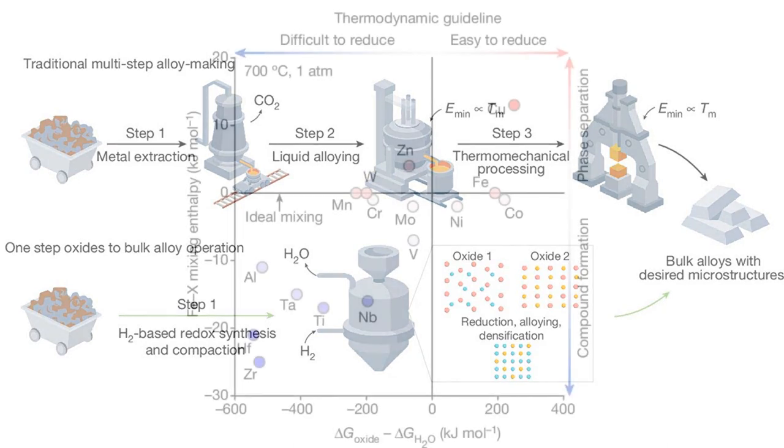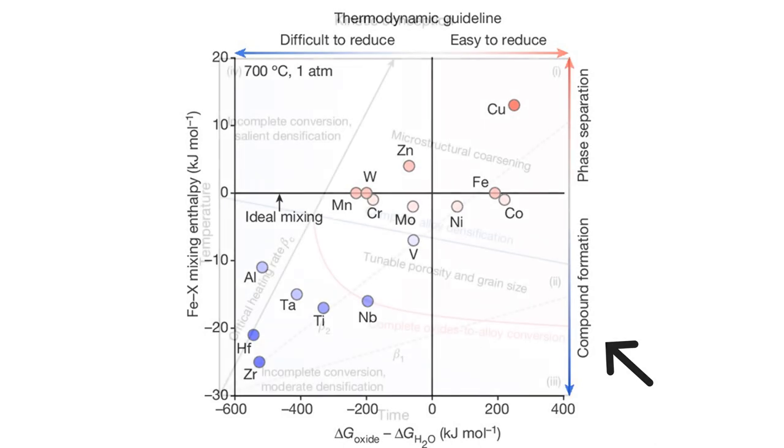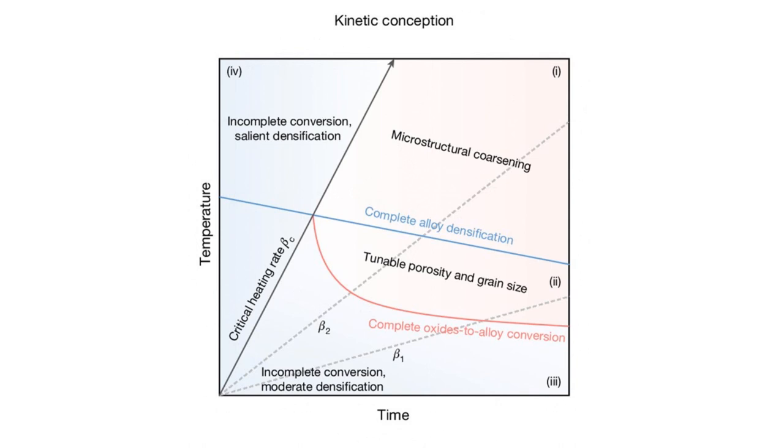We also adjust the temperature to allow diffusion and pore-closing to arrive at desired microstructures. This is done on solid thermodynamic grounds, as shown in this slide, where we pick certain combinations of metals prone to undergo co-reduction by hydrogen. Not only is the thermodynamics well-guided, but so is the microstructure design — running these processes to avoid coarse graining while allowing for surface diffusion and pore filling.